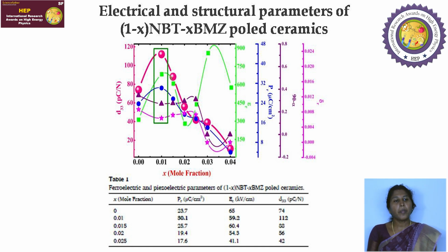So from the figure we can observe that for x equal to 0.01 mole fraction of BMZ substitution, we get the highest d33, highest Pr and almost moderate epsilon r, that means dielectric constant. In this case, the structural properties, that is rhombohedral lattice distortion and lattice strain, are reduced. So due to the reduction of the rhombohedral lattice distortion as well as the lattice strain, the non-180 degree domain reorientation is enhanced. So we get enhanced ferroelectric, dielectric as well as piezoelectric properties.